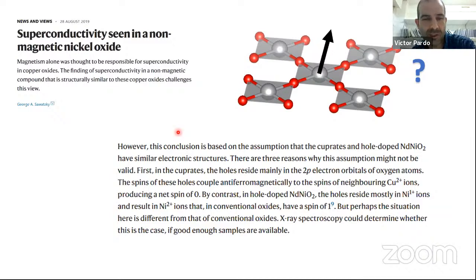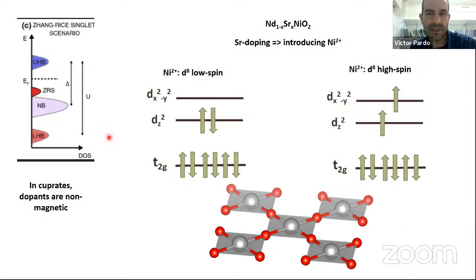Remember that in the cuprates, when you dope, you have these Zhang-Rice singlets, you have non-magnetic dopants. So is the situation in nickelates different? Are we doping with a magnetic dopant? So we said, okay, well, let's calculate it. We have to calculate what the energetics of this situation are. So we want to know if you dope with a nickel 2+, whether this is low spin or high spin. If it is low spin, then you would have this situation favored, and if it is high spin, then you have this S=1.